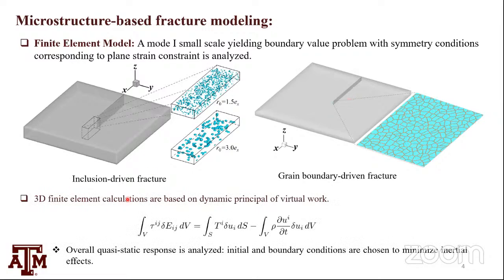And the method we're going to use is finite element explicit. We take this and put it in the finite element code, which is dynamic and follows the dynamic principle of virtual work. So, finite element explicit. Why explicit? We're interested in quasi-static. Explicit, because we're going to simulate crack growth, and it's not easy to make an implicit code converge. So we go with the dynamic principle of virtual work. As long as we follow things in explicit calculation right, we get a reasonable convergent result.